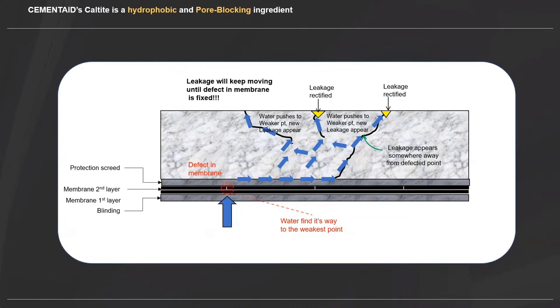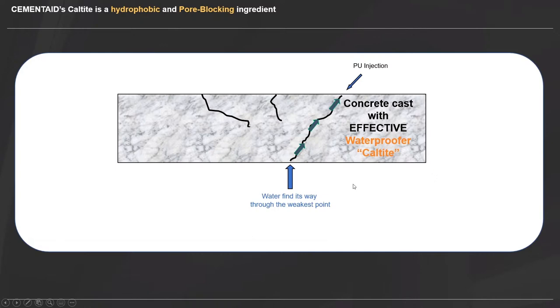When it comes to repairing cracks, if we've used a membrane and the membrane for any reason failed, water will travel along the gap between the membrane and the concrete, and it will find a crack. If it's a through crack, it will come out. So the normal procedure then may be to inject that crack and stop the leakage. But unfortunately, with normal concrete, water will transpire and even reach a crack which is not a through crack, and you're going to have another leak here and another leak here, and you can chase this water around a tunnel structure or a basement structure forever and a day if the membrane has failed, because you can't actually find the hole in the membrane. Whereas if this is membrane-free HPI concrete, if you've got a through crack, that is the only way that water gets through, a through crack right the way through the section. And it's very simply resolved by just injecting PU resin into that crack.